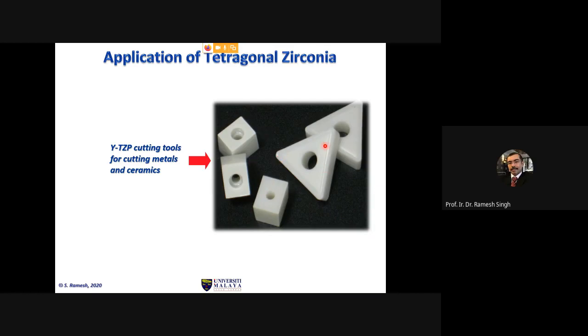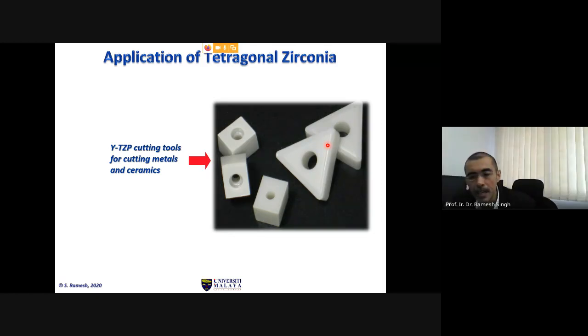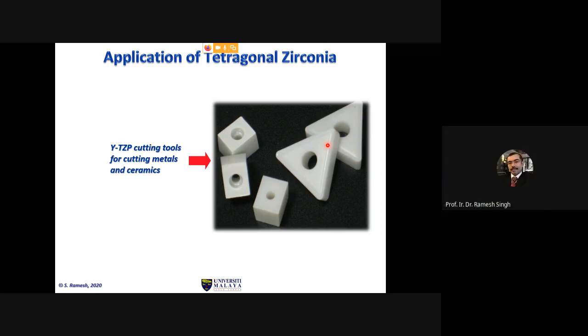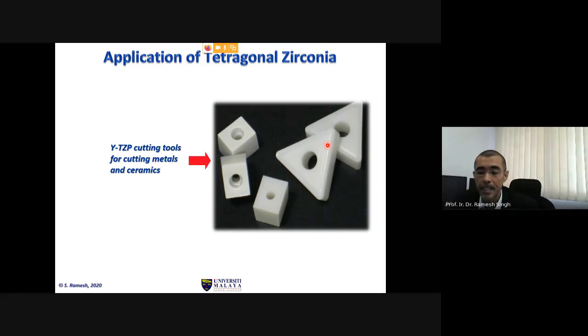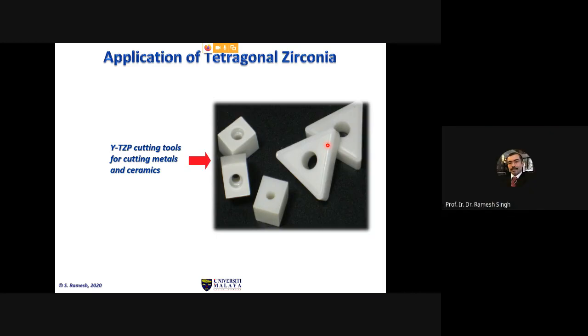And I have to design the whole process. I mean, because the material comes in powder form, and I have to think about near net shape forming ability to form the component without needing to undergo surface finishing and so on, because grinding of ceramics is very expensive, because ceramics are very hard material and you have to use diamond tool to grind them. So in order to avoid excessive grinding, we have to do near net shape formation. So we need to design the mold and die in order to press directly into its shape, so that after we sinter it, we will get the final shape of it. So a lot of thought process have to be put into the development of the cutting tool.